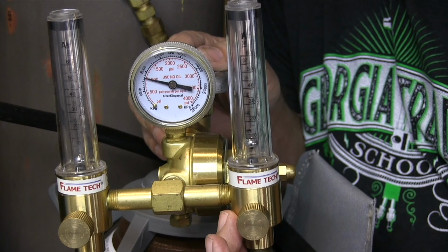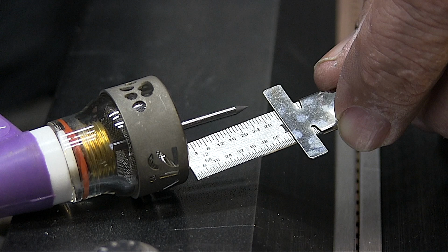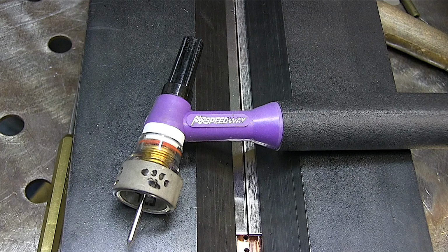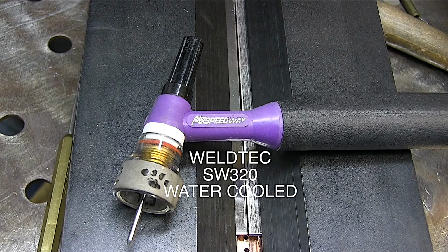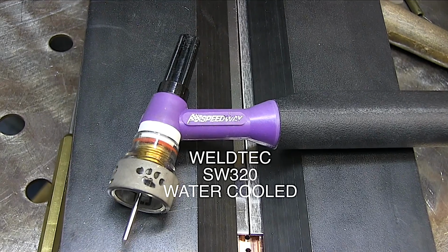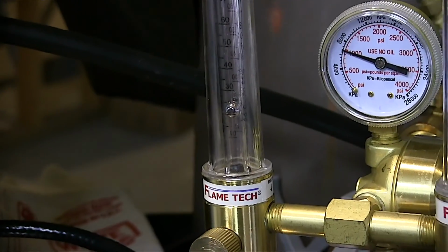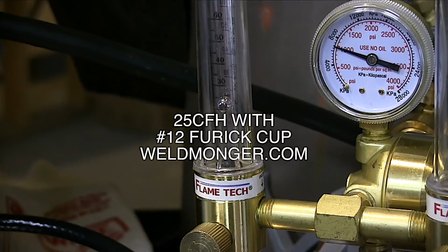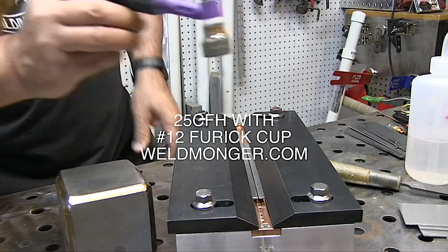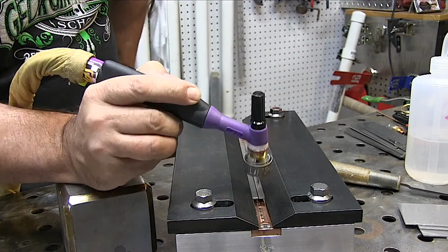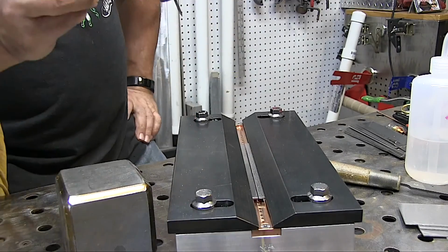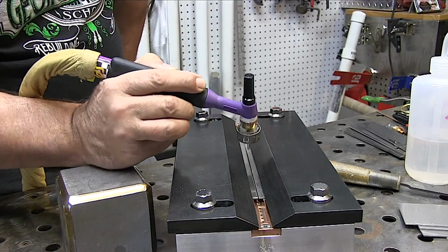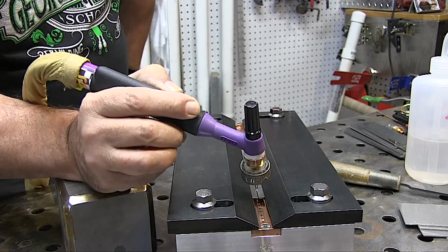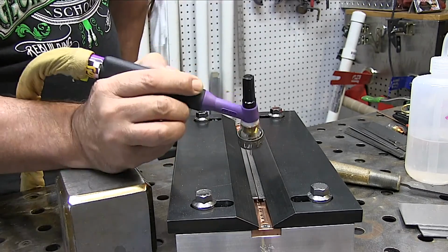10 CFH on the fixture, and I will use some small pieces of tape to tape off the unused portion of the argon trough. This is a nice Speedway SW320 amp water-cooled torch I'll be using, and on that number 12 cup I'll be using about 25 CFH. This stands quite a ways up off the table because it's pretty thick, so I'm using this little block that I made a while back to get comfortable with. That's what I'll do for this stainless joint.